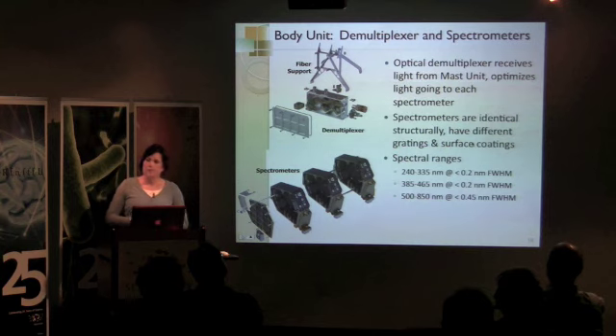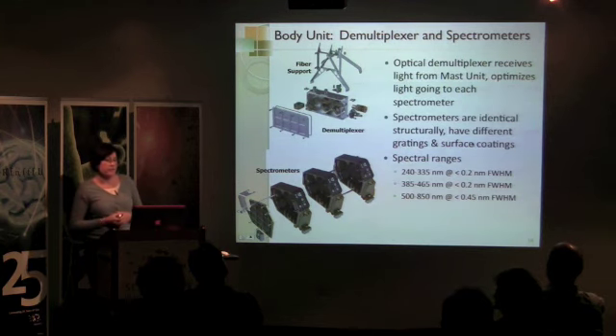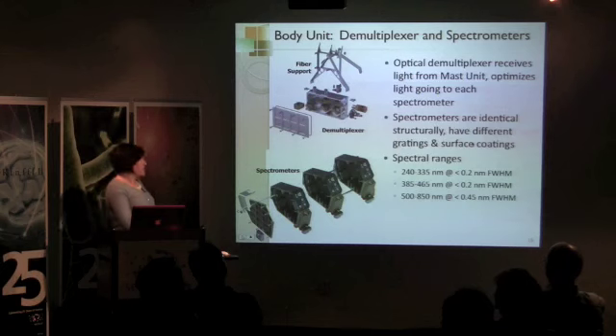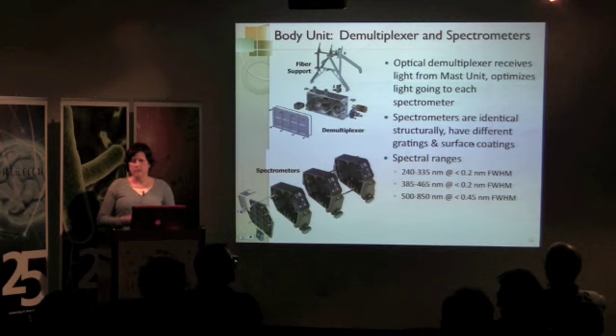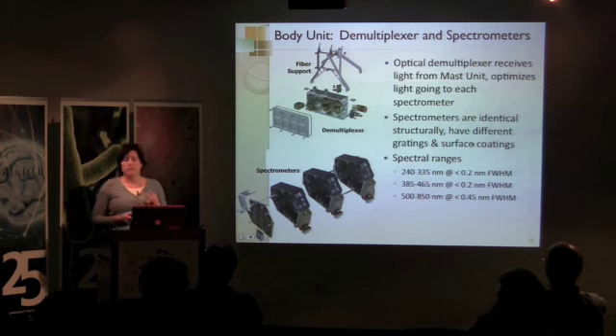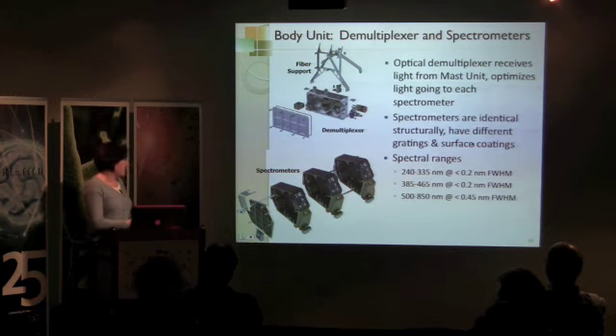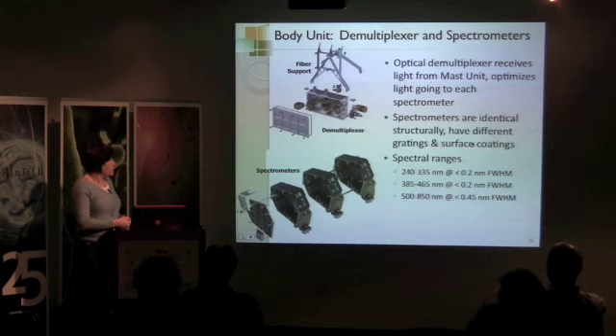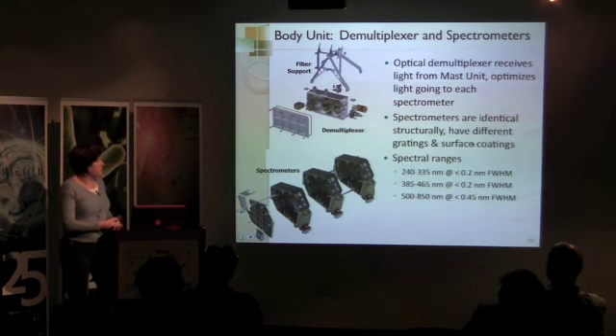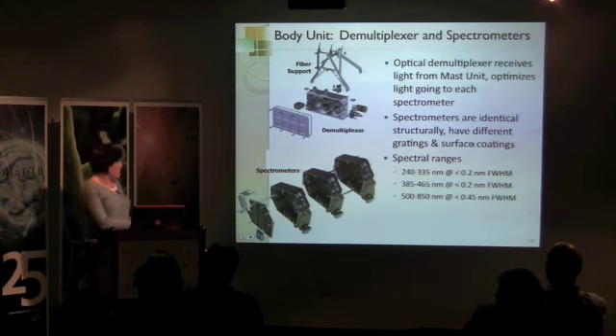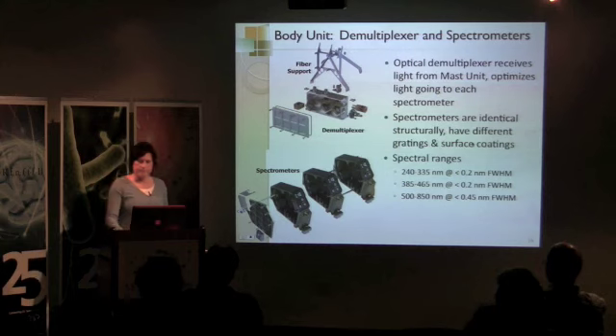The body unit, which was built at Los Alamos, includes a demultiplexer and spectrometers. As I just mentioned, the demultiplexer will receive light from the Mast unit, and it's optimized to send light to each spectrometer. These spectrometers are identical structurally, but they have different gratings and surface coatings. And this just again shows the different spectral ranges for each spectrometer. They're essentially stacked together on the body of the instrument. And for the UV and Vis, there's higher spectral resolution of 0.2 nanometers, and then it goes down to slightly lower resolution over the larger spectral range of 500 to 850 nanometers.